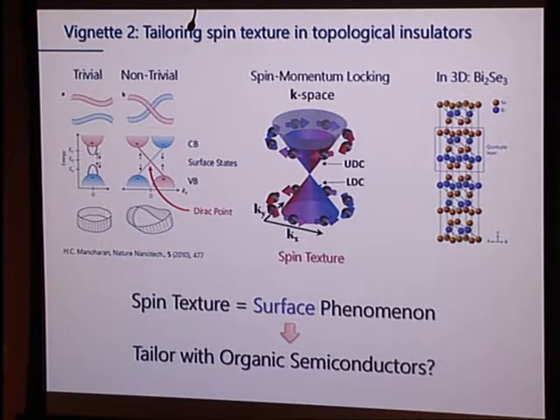The classic material that does this is bismuth selenide. It's a van der Waals layered material that comes in multiple layers in one unit cell. Now, for this particular type, and because it's a layered material, the spin texture, the fact that spin and momentum are connected with each other, is a surface phenomenon. So that suggests that perhaps you can actually tailor this.